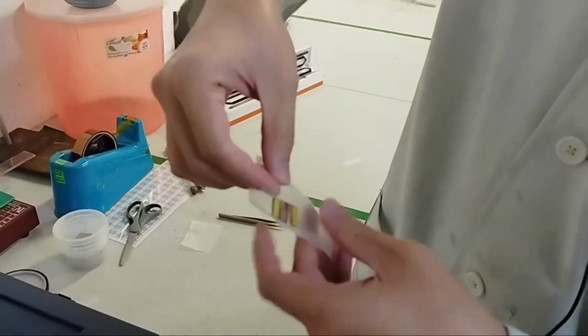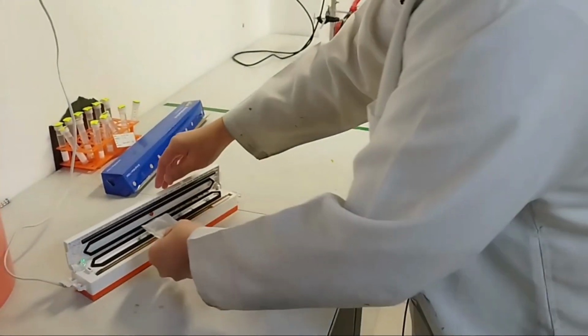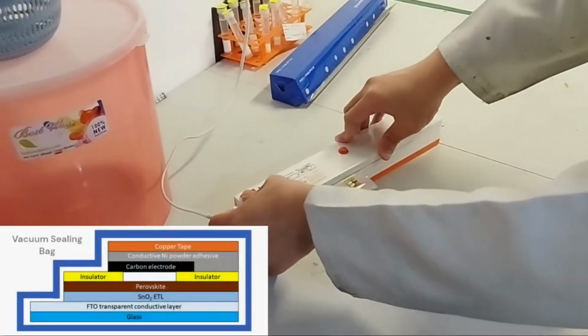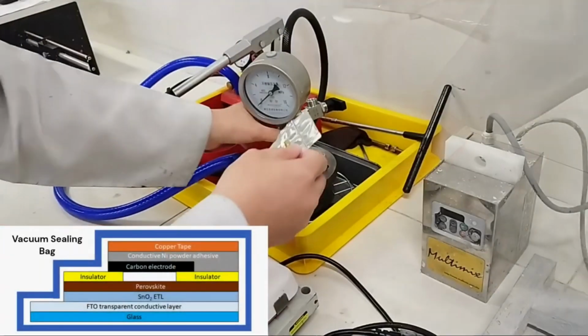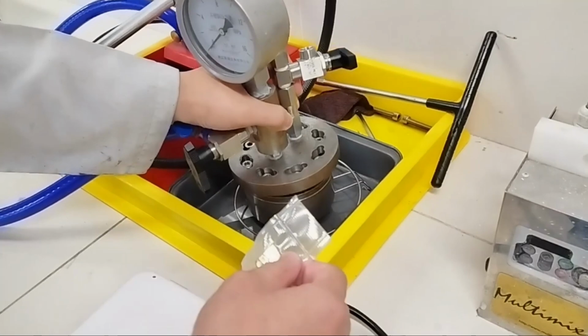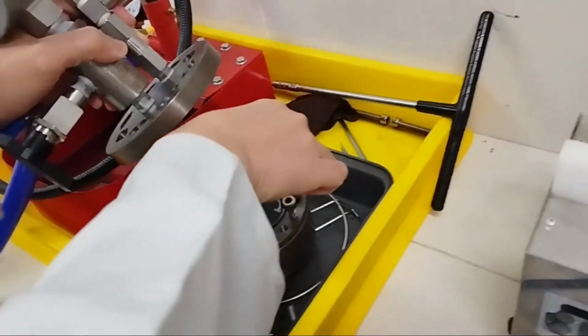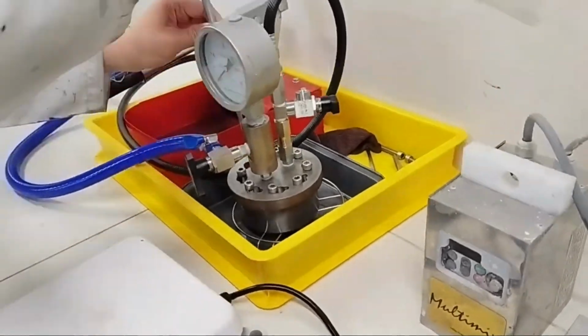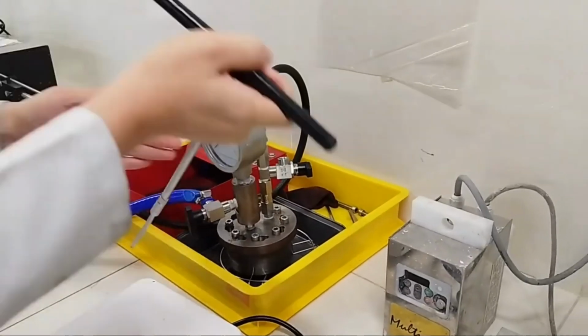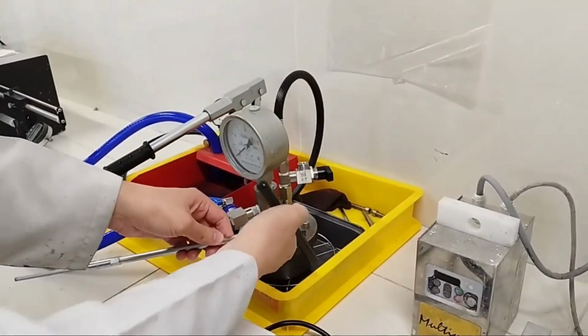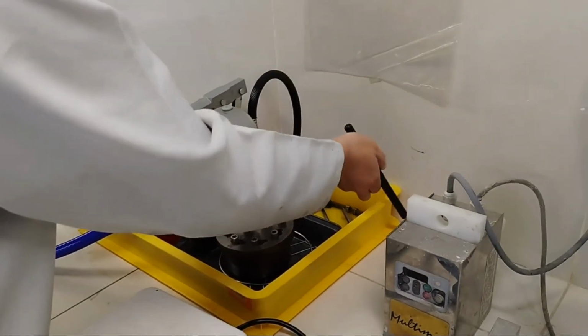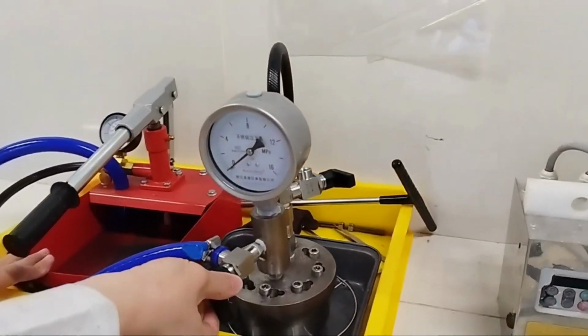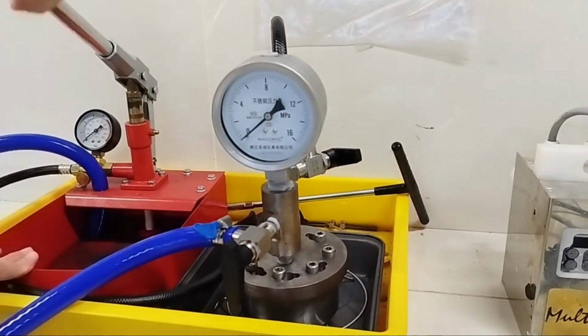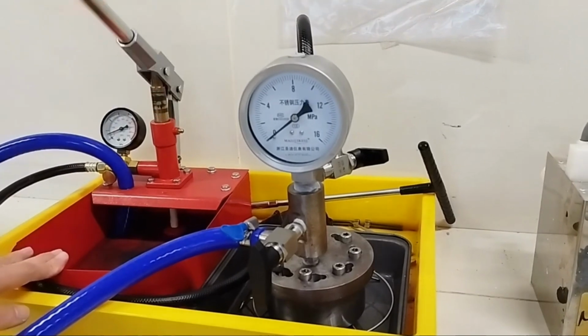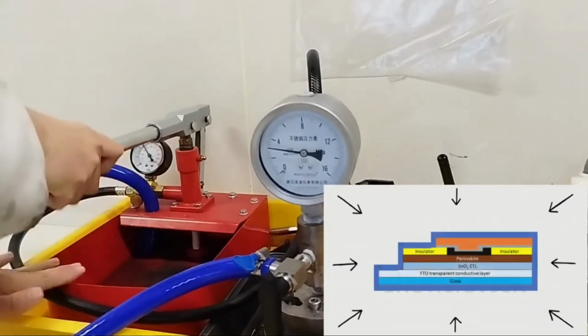Here's how it's done. First, I vacuum sealed the prepared perovskite film with pre-arranged carbon electrodes into vacuum sealing bag. Then, I place the bag inside a custom hot isostatic chamber and tighten all chamber bolts to ensure a secure seal. I then introduce silicone oil into the chamber using a manual hydraulic hand pump jack to increase the pressure inside the chamber to roughly 5 to 6 megapascal.